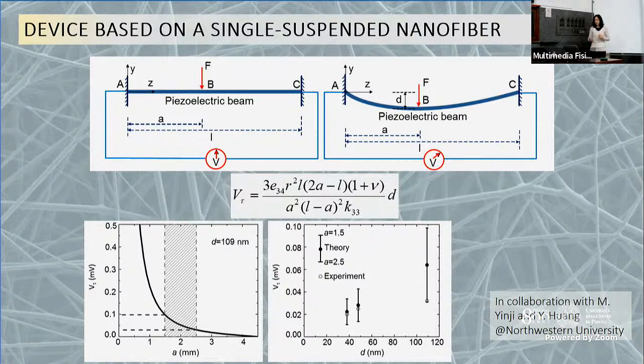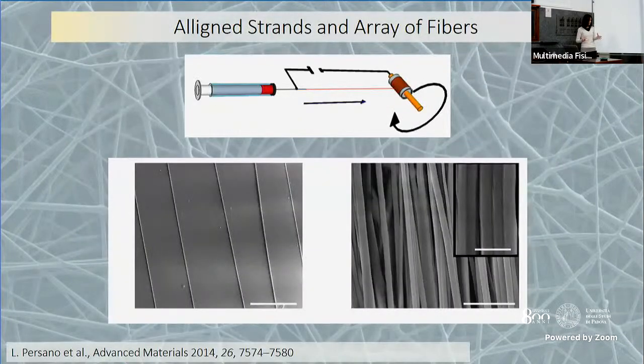And what we got is that the best agreement between theory and experiments in our case was where this parameter A is in between 1.5 and 2.5 millimeters. So this is an additional application of this kind of material and devices. But what happens if instead of using one single fiber, I use many fibers? And what's the difference if I use fibers which are isolated, so which means they are far away from each other, or if they are in a dense array configuration?